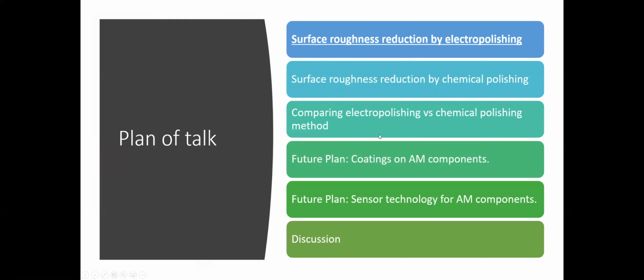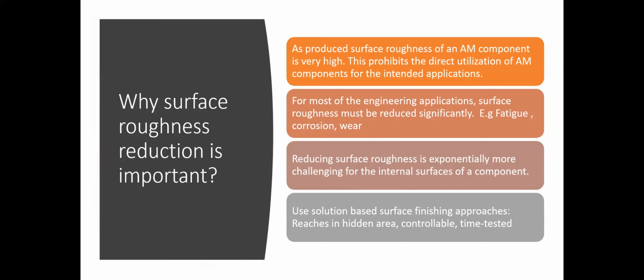As I mentioned before, somebody wants to put nickel coating on the additive manufacturing components. The first thing is that they need to improve the surface quality, because as-produced metal 3D printed parts are pretty rough, with roughness of the order of 20 micron Ra. It is as rough as if somebody does not shave for a couple of days, and if you put your hand on your face, it feels like that. So in order to do nickel coating, it needs to be smoothened out first.